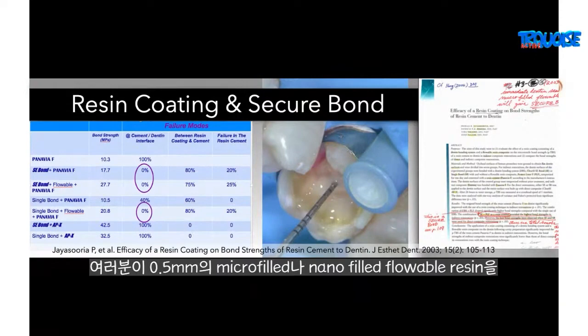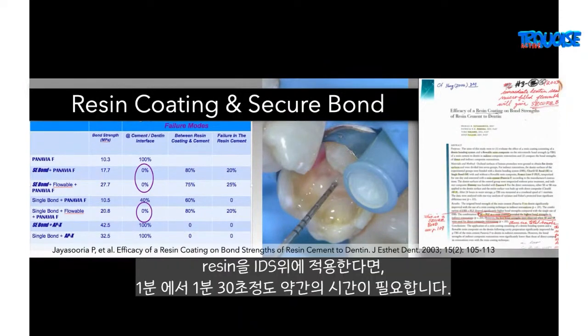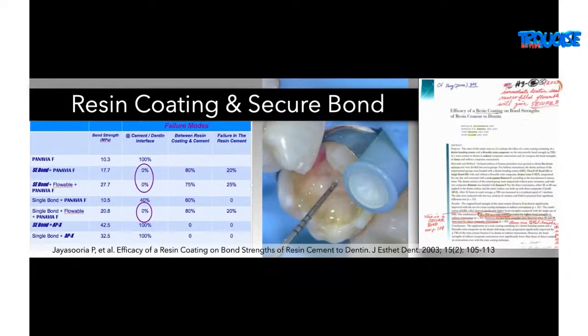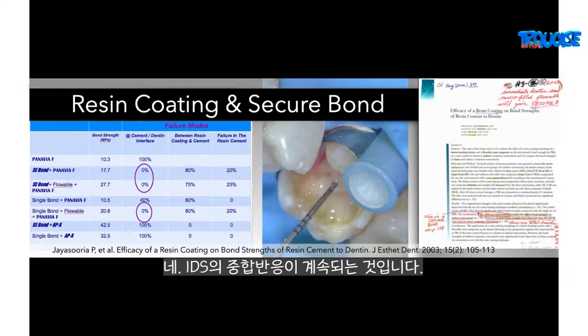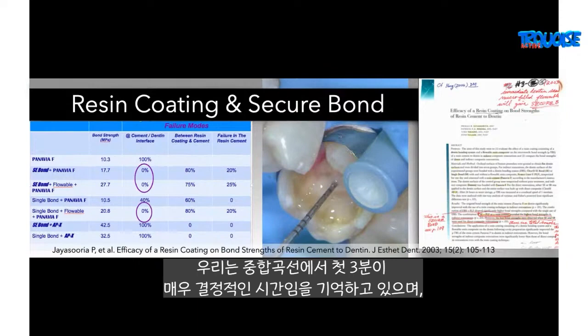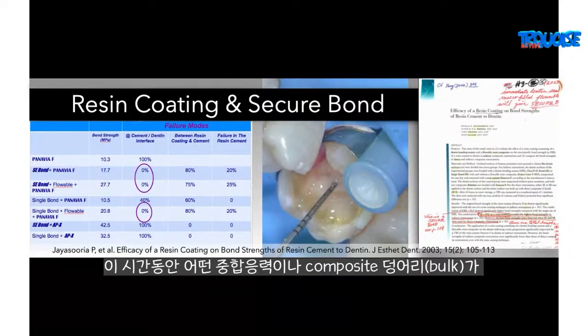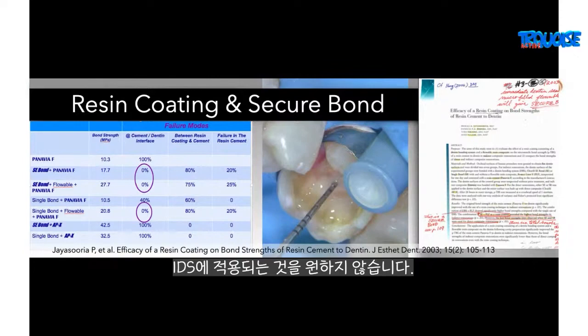And what happens is when you put this 0.5 millimeter of a microfilled or a nanofilled flowable on top of your immediate dentin sealing, it takes a little bit of time, about a minute to a minute and a half. And what's happening during that minute or minute and a half? Well, the immediate dentin sealing polymerization reaction is continuing. And we remember that that curve at 3 minutes is really the critical time. You don't want to have any polymerization stress or bulk of composite on top of your immediate dentin sealing in the first 3 minutes for sure.